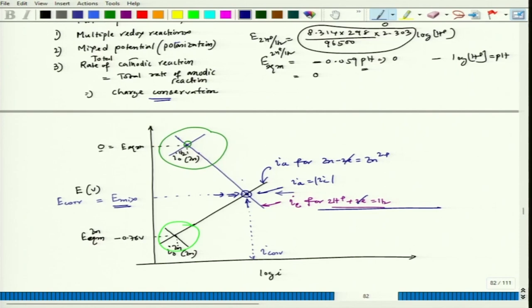Now, as we go up, let us say I consider that I can go up. How can I go up? I can send positive current, or IA, to the zinc from an external source and I can take it in the positive direction. So, I can take the potential here. And when I take the potential here, an interesting observation is that though the hydrogen evolution rate is going down, because the current density corresponding to hydrogen evolution, which is IC, is going down as compared to the current density at E corr, which is this. Fine. So, that means the hydrogen evolution rate would reduce. But interestingly, I could see that the rate of zinc dissolution, which is IA, this is let us say I prime and let us say E prime, this I prime is more than the IA corresponding to I corr, or corresponding to that potential point, which is E corr.